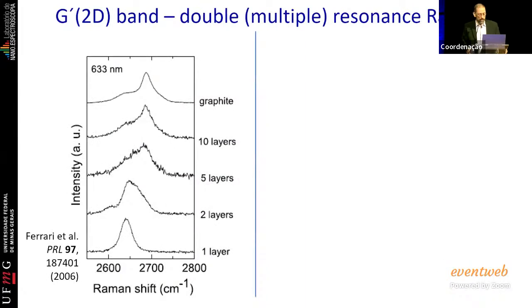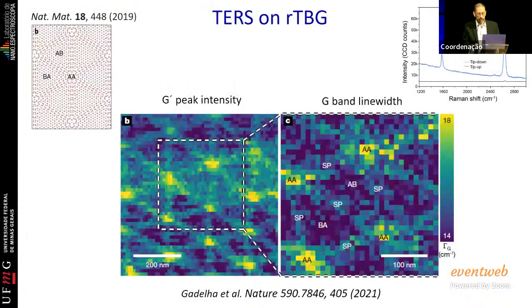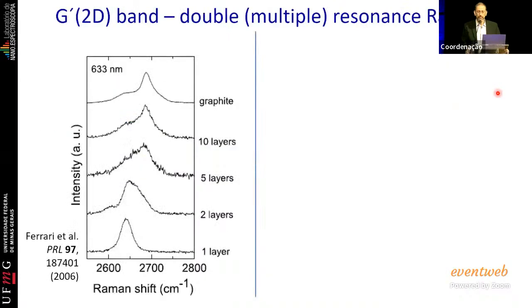So, for example, let's talk again about this peak that I told you. It's a peak related to a second order hexagon breathing, and it was shown in 2006. This is one of the most highly cited papers in the literature, tens of thousands of citations. The reason why this paper is very important is because these fellows showed that the shape of this Raman peak tells you how many layers you have in the system.